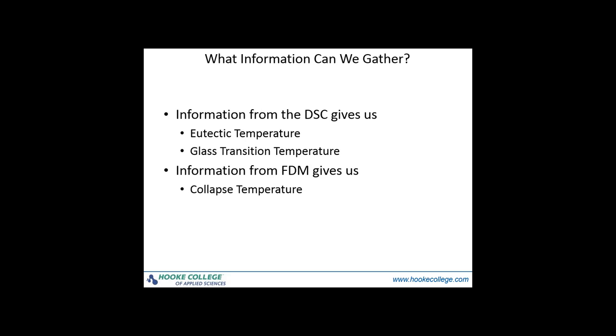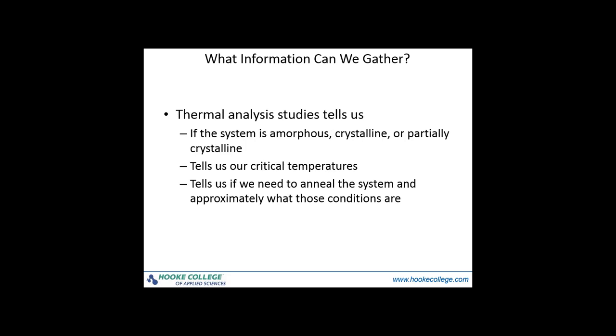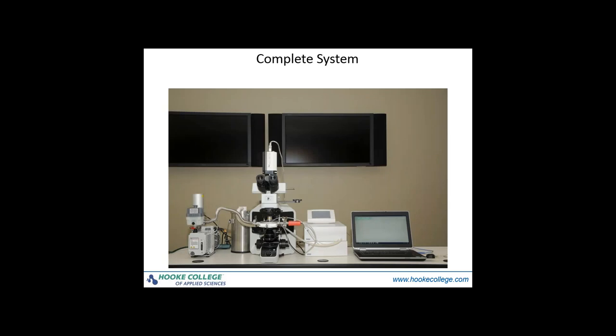One of the main things is that the glass transition can be anywhere between 5 to 15 degrees different than our actual collapse temperature. And if we are able to freeze dry warmer, we exponentially increase the rate of drying of our product. So if we're actually able to freeze dry our product at minus 25 instead of, say, a glass transition at minus 34, we're giving it less energy, so it's costing us less to produce, and it'll freeze dry a lot quicker. So again, thermal analysis studies tell us if the system is amorphous, crystalline, or partially crystalline, tell us our critical temperatures, and also tell us, if we need to anneal the system, approximately what those conditions are.